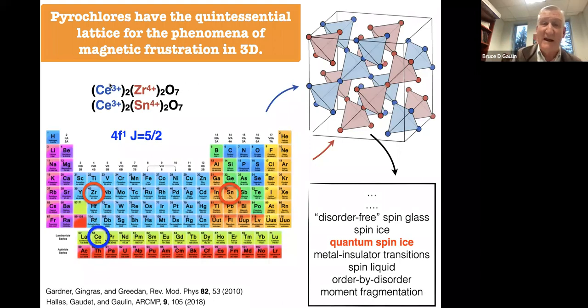At any rate, one of the interesting things about this pyrochlore structure is that both the rare earth site, which is shown in blue, and the transition metal site, which is shown in red, independently lie on a network of corner-sharing tetrahedra. But because the red network is a non-magnetic network, we're only going to focus on a single so-called pyrochlore network, which is a single network of corner-sharing tetrahedra.